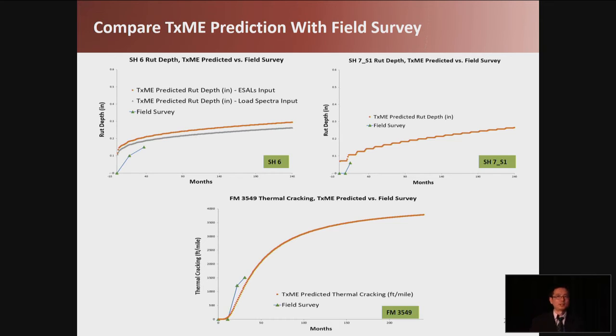So basically, for the 11 sections, because the time is not long, more than half of them didn't show any rut depth or any cracking. And our prediction also didn't show any crack or rut at this time. For the test sections like SH6, SH7 section 1, and FM 3549, we did see some failures: the first 2 showed rut depths, and this one showed thermal cracking.